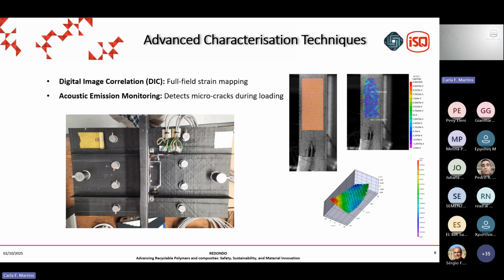Digital image correlation is also something that is not entirely new. It's been around for some years, but it's particularly useful in composites, because with digital image correlation, we can have 2D or even 3D images of our test specimen or test component, and we can have a full field strain mapping, like in finite element analysis, where we produce those stress, strain, whatever distribution maps for our whole component or specimen of interest. But then, besides the overall behavior of our component or specimen, we can then analyze in more detail some particular areas of interest, like stress concentrations or defects or whatever.